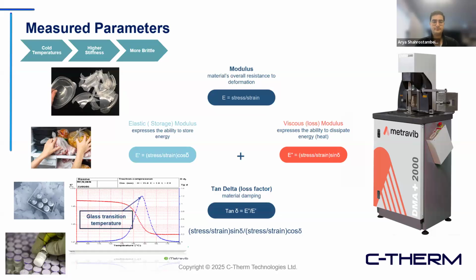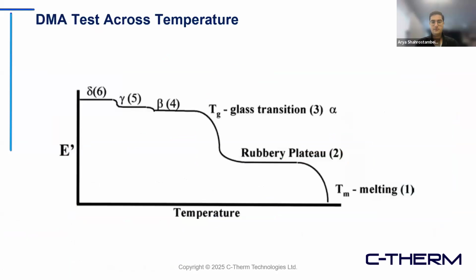However, in order to mechanically deform the samples, you need high force capabilities, and the DMA Plus series of Metravib instrument can definitely provide you that tools for your testing. So this is a temperature sweep test using dynamic mechanical analysis technique. And as you can see, glass transition temperature happens at alpha transition, the midpoint. And before that is exactly the point that material can be more prone to mechanical failures and becomes more brittle.